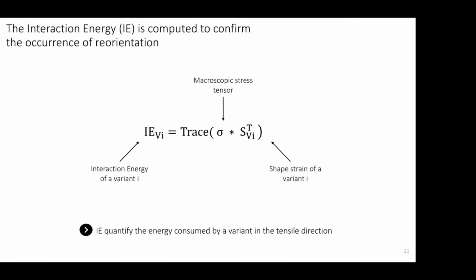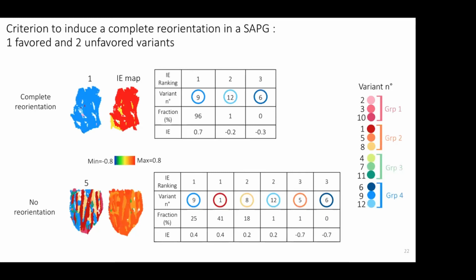And what is the physical signification of the interaction energy? It's just the energy which is consumed by a variant in the tensile direction. So this is expressed as an energy, but you can also see it as a deformation. So it's also the deformation that can be given by a variant in the tensile direction. So we tried to compute this value on the experimental case, for the two extreme cases: the first one of a complete reorientation and a second one of no reorientation.